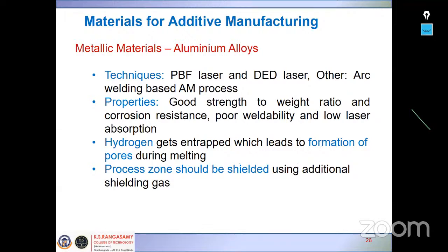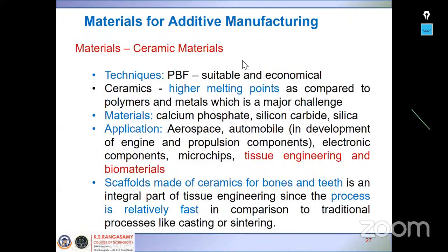When you use aluminum alloys, you have to carefully control the environment. When you melt aluminum alloys in the normal environment, hydrogen gets entrapped, which leads to the formation of pores during the melting process. So you have to use a specially designed, closed zone. The process zone should be shielded using additional shielding gas, and then you can avoid the entrapment of hydrogen during the melting process. Once pores are formed due to hydrogen entrapment, the product can be weakened in strength. So we have to be very careful when processing aluminum alloys in the 3D printing environment.